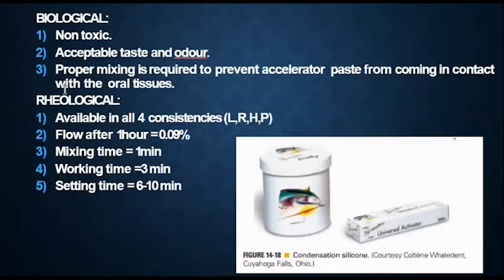Coming to the properties, it is non-toxic. It has acceptable taste and odor, and proper mixing is required to prevent the accelerator paste from coming in contact with the oral tissues. So it's available in all the four consistencies and has a flow of 0.09%, mixing time 1 minute, working time of 3 minutes, and setting time of 6 to 10 minutes.